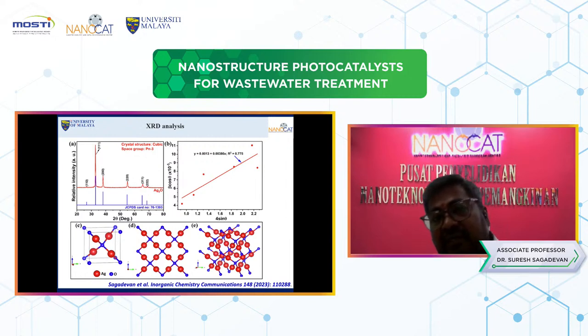And as well as we calculated by WH plot, and also we calculated for high crystallinity by using the WH plot. And also this material, we proposed a ball stick model for the structure of this silver oxide. You look at here, the cubic shape, very clearly you can see from this ball stick model of the crystal structure of this silver oxide. And as well as we calculated bond angle, bond length, and crystallographic parameters using this software.